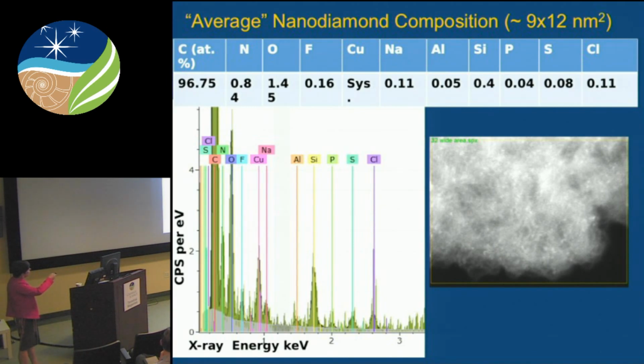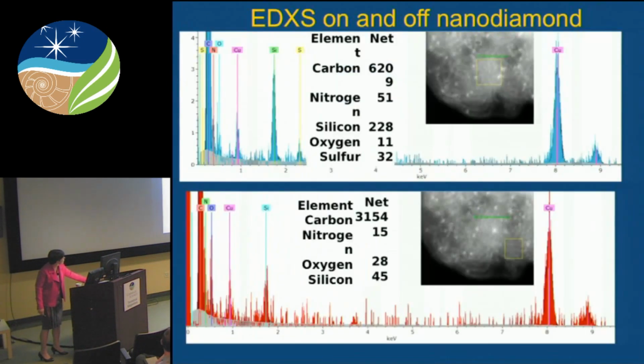So I already told you the nitrogen there is at 1 to 3 atom percent. There's oxygen, which can be enhanced by the treatment of the residue to isolate this from the meteorite. Fluorine is, again, a product of the dissolution from the meteorite. Sodium, aluminum, silicon, phosphorus, sulfur, and chlorine may or may not be associated with the host meteorite, so it's extremely difficult to get the chemistry clean enough that you've washed away every impurity atom that came out of the meteorite.